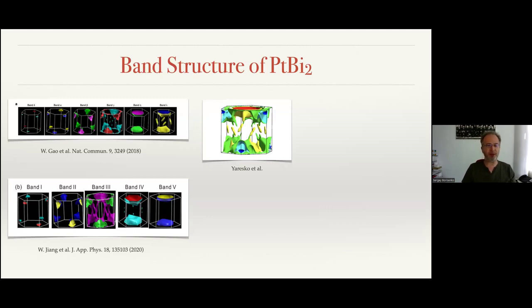The band structure of trigonal platinum bismuth 2 is pretty difficult. We have 5 bands, and even according to different calculations, you can get 6 bands crossing the Fermi level. So the Fermi surface at first glance is very complicated, but if one has a closer look, there are quasi two-dimensional objects. One could see some kind of layered structure, and this probably explains why the material is cleavable. To make an ARPES experiment, one has to cleave the crystal, one of the methods to prepare an atomically clean surface. This is probably the explanation why it is cleavable, although it is very three-dimensional according to the number of bands and the topology of the Fermi surface.